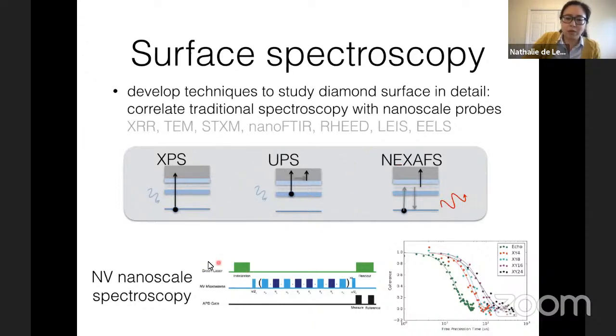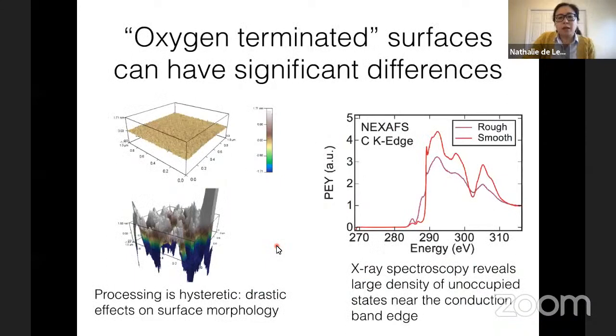And the reason that we zeroed in on these techniques is that we could then correlate information that we saw with something a little bit more sophisticated than just asking the NV center if it had a long coherence time. You can do some nanoscale spectroscopy to figure out what's going on in the local environment of the NV. So I'll cut a fairly long story a little bit short and just give you the highlight reel of things that we discovered about the diamond surface.